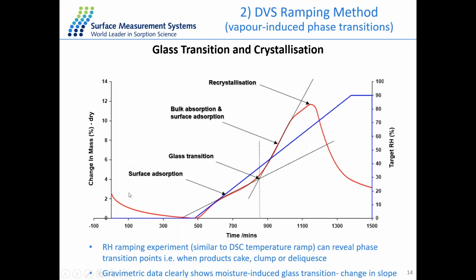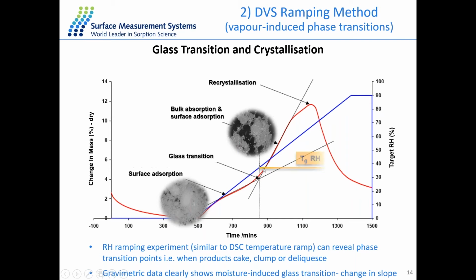And it's quite clear that the water sorption first is losing mass, caused just by the flow of the carrier gas. And the sample mass is increasing slowly due to the surface sorption of the water molecules. And after a certain point of humidity, the sample will increase dramatically because the water molecule here is not only on the surface, but also penetrating the surface and going to the bulk of the material. So it's a bulk dominated mechanism. And the transformation between the surface sorption and the bulk sorption can be taken as the glass transition. And from the slope before and after this point, we can get the glass transition point. And we can also calculate the glass transition humidity for this sample at certain temperature.